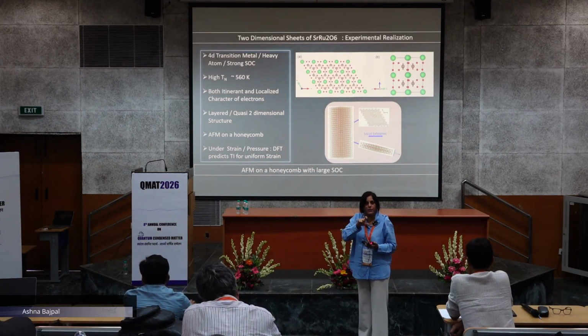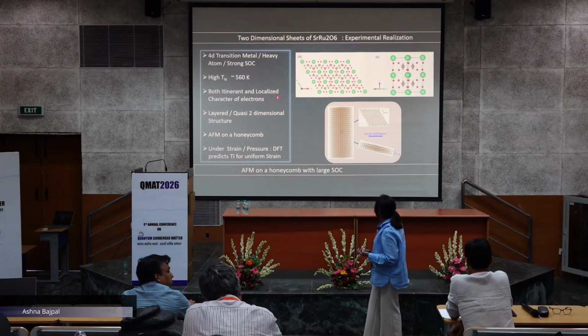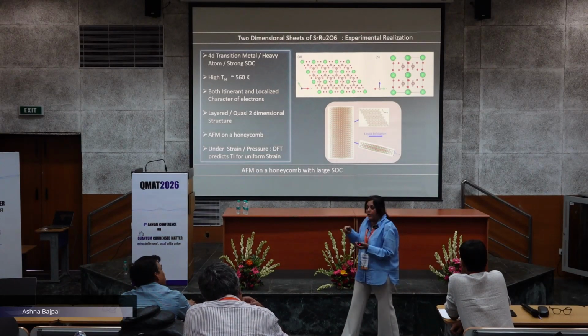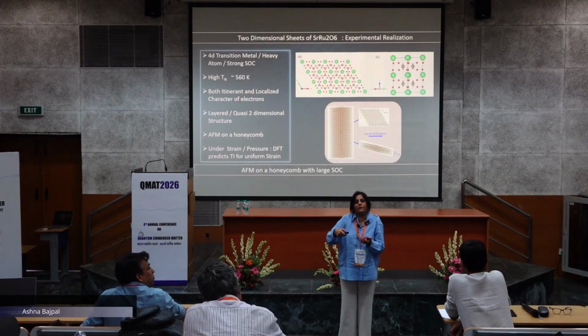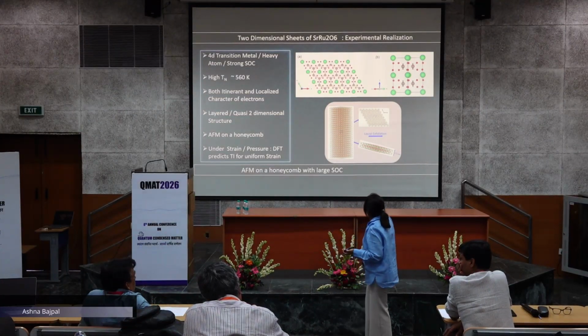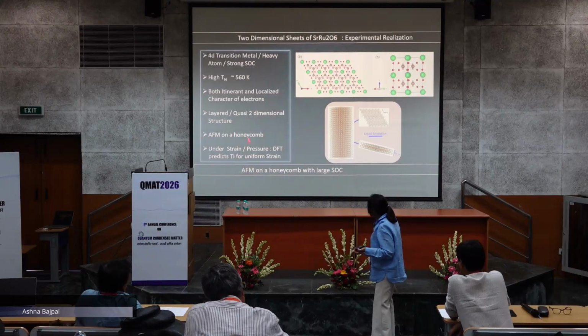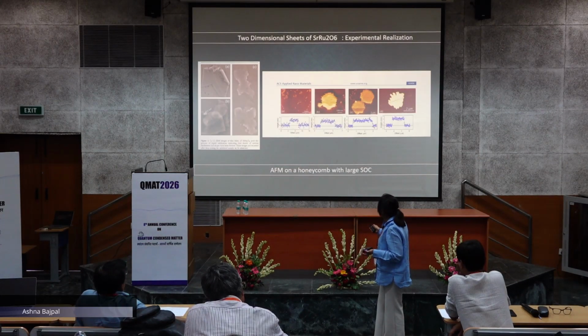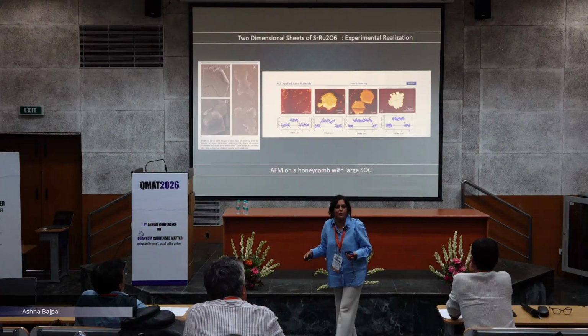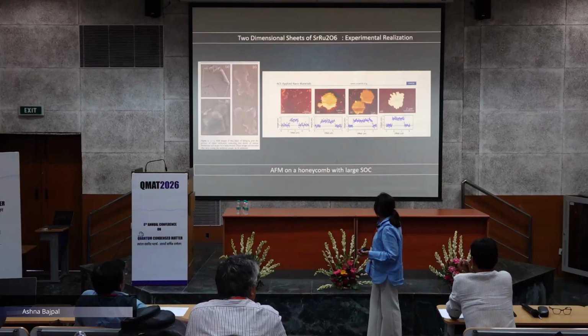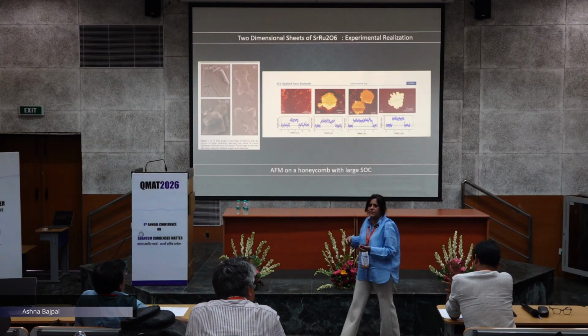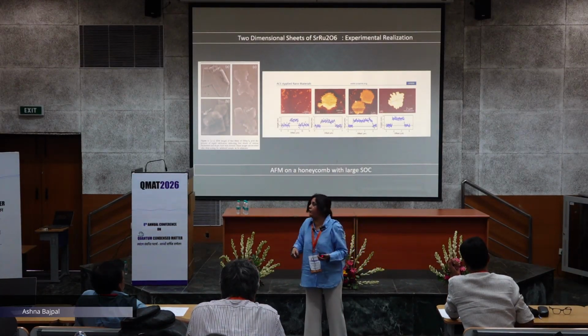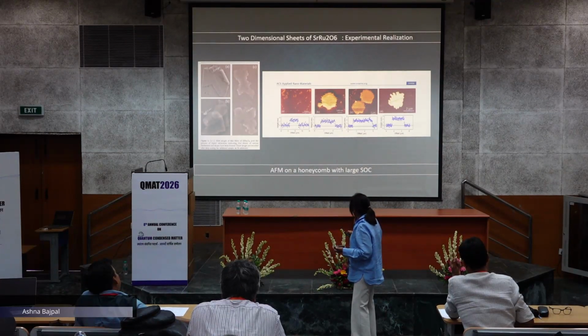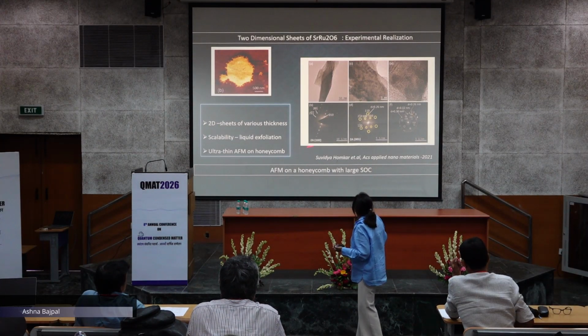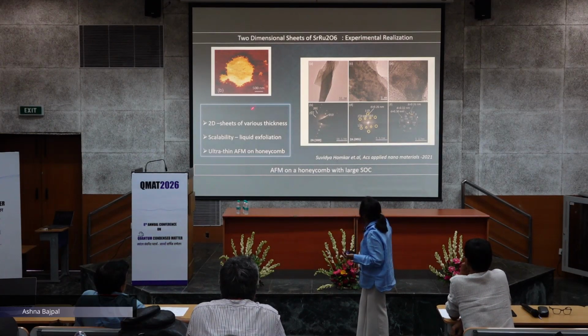In addition, you can dilute the system, so all these possibilities are there. In a way, putting your antiferromagnetic hexagon under strain is one of the very interesting games you can play, and therefore we tried this liquid exfoliation. You can see the results, the SEM sheets for these systems, and these are the AFM measurements which say that 2 to 5 monolayers we could exfoliate in this system. And these are some of the TEM results showing the nicely exfoliated sheets.